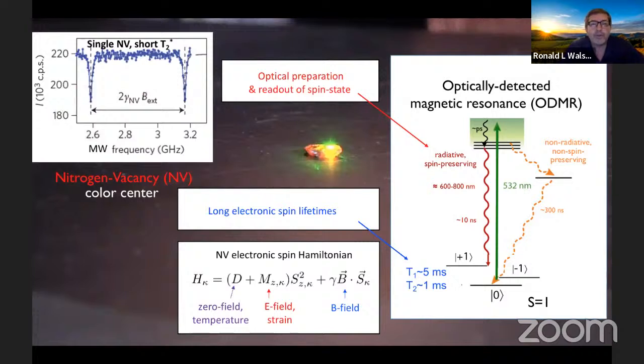So let me show you how this would work in practice. And I'll show you first for a single NV, and then later for an ensemble of NVs, when you have many NVs. Here is an example of data, ODMR data, optically detected magnetic resonance data for a single NV. And in this case, we have a short T2 star, this is the dephasing time. I chose data from a short T2 star example because it washes out the hyperfine structure and makes the diagram